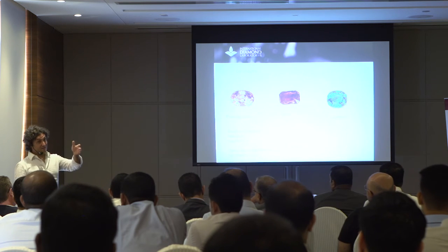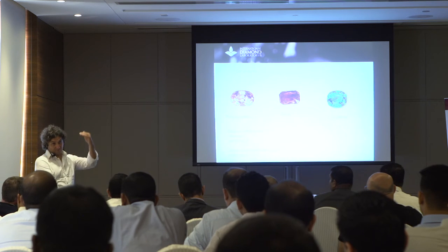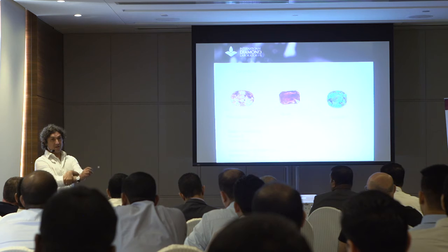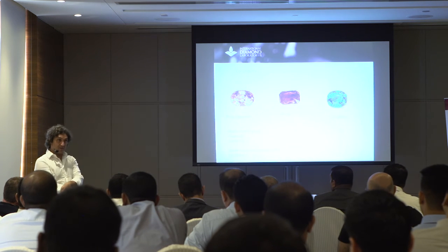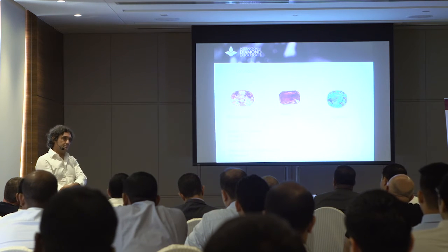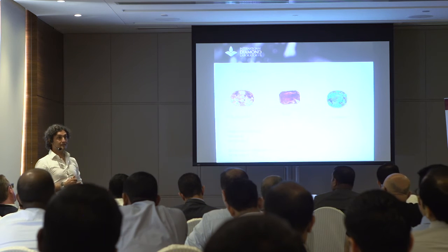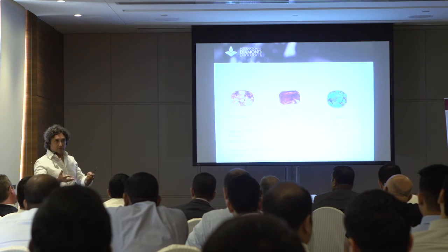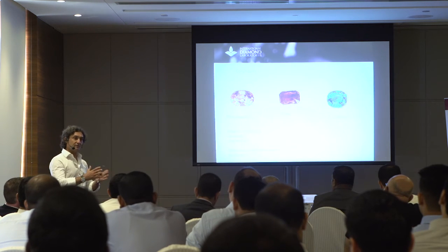For ruby, it is the same principle, but because ruby has a much higher refractive index, you cannot use the same material. You need to use a kind of glass which contains lead, which has a very high refractive index. Well, it's more durable now because they are improving, but you need to go close to the refractive index of that stone.